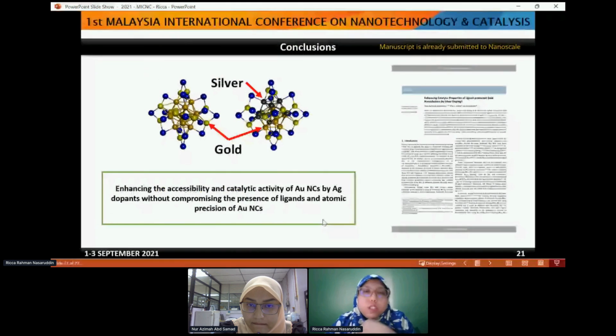So this is the conclusion for the study, and the manuscript is already submitted to Nanoscale. We realized that we can increase and enhance the accessibility and catalytic activity of gold nanocluster by silver dopant, without compromising the presence of ligands and also the atomic precision of the gold nanocluster. So it means that the metal nanocluster.